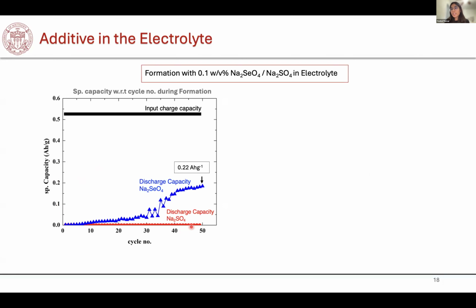To our surprise, or what we already expected, in the formation capacities, since sulfates cannot be kinetically converted back to sulfides, there is no depassivating agent, and during the formation, the discharge capacity sits at zero. Whereas when selenium is present in the battery electrolyte, the electrode starts forming very slowly until a stable discharge capacity is attained, around 0.22 ampere hour per gram, very close to what we were seeing when the additive is present in the electrode itself.